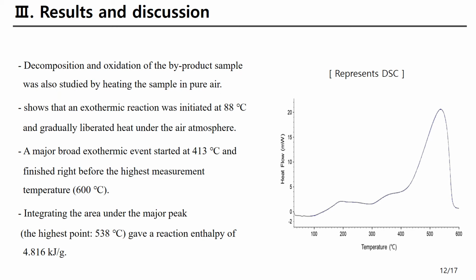The decomposition and oxidation of the byproduct sample was also studied by heating the sample in pure air. This shows that an exothermic reaction was initiated at 88 Celsius degrees and gradually liberated heat under the air atmosphere. A major broad exothermic event started at 413 Celsius degrees and finished right before the highest measurement temperature. Integrating the area under the major peak gave a reaction enthalpy of 4.816 kJ per gram.